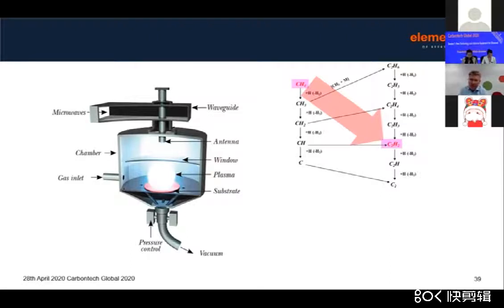So particularly when you're trying to produce materials with high phase purity, or you're engineering material for high thermal conductivity, for high optical transparency, or for high boron content, it can be very useful to be able to manipulate and access other areas of the chemistries that other types of CVD process find difficult to access, particularly, for example, the hot filament growth technique, which really limits the temperature of the plasma and thus limits the chemistries that you actually can see. Okay.